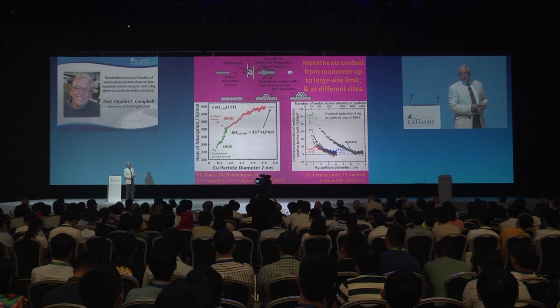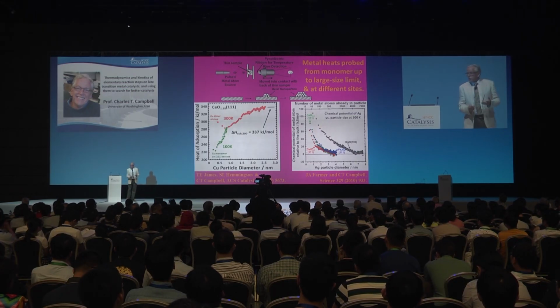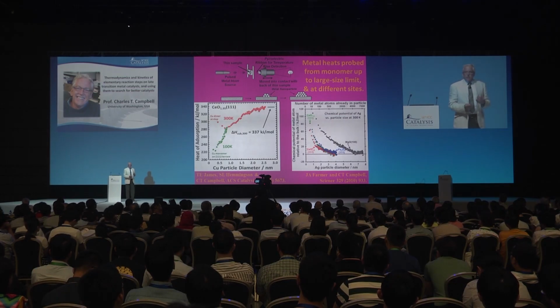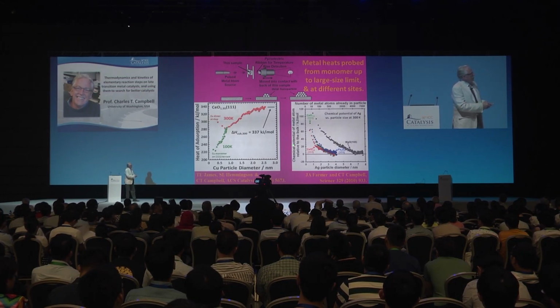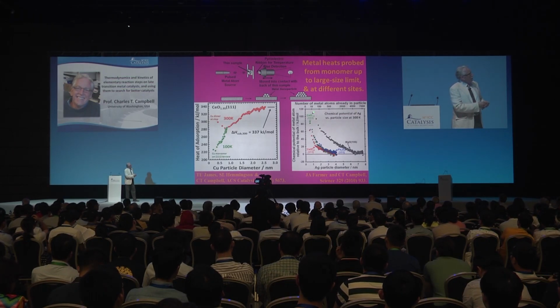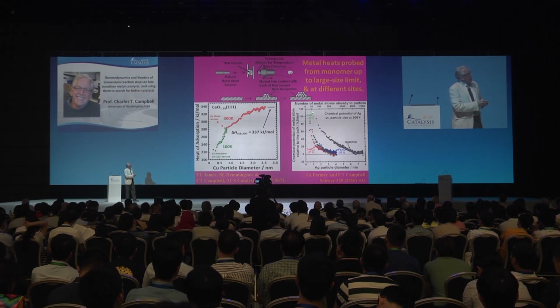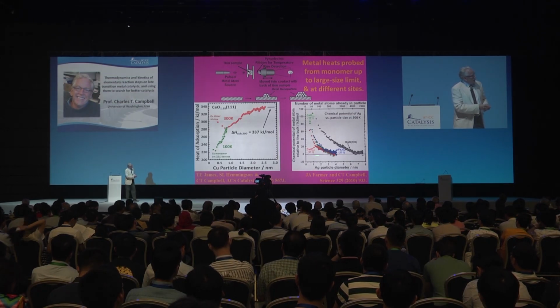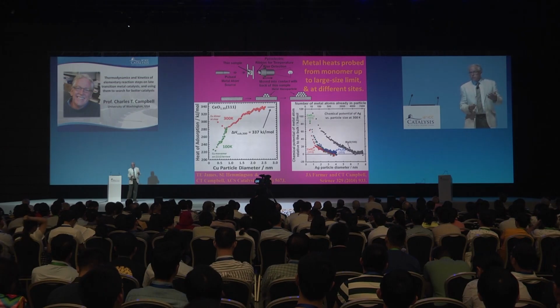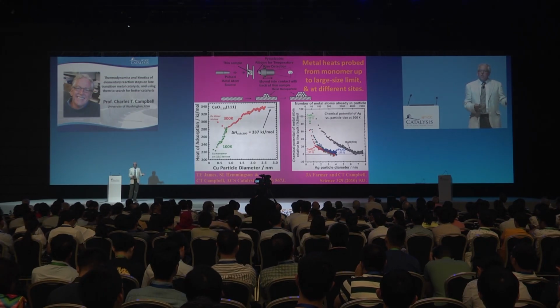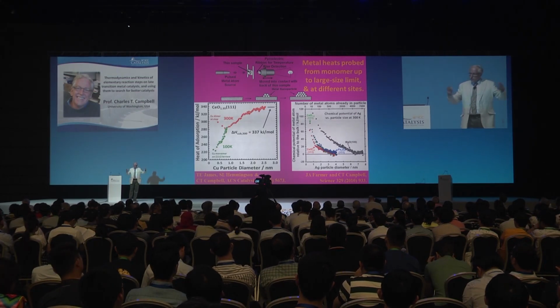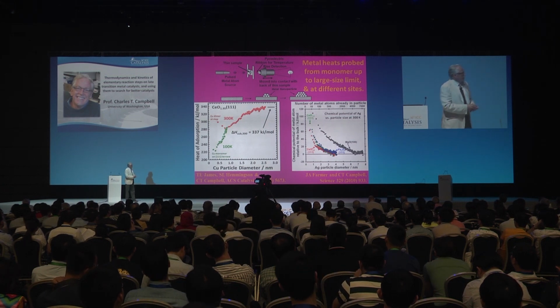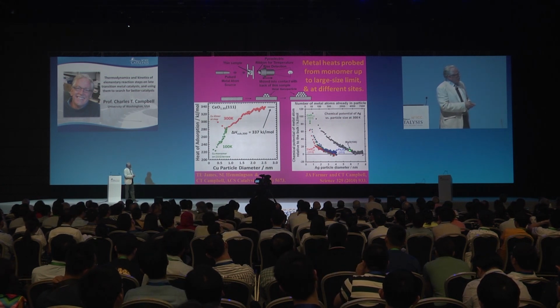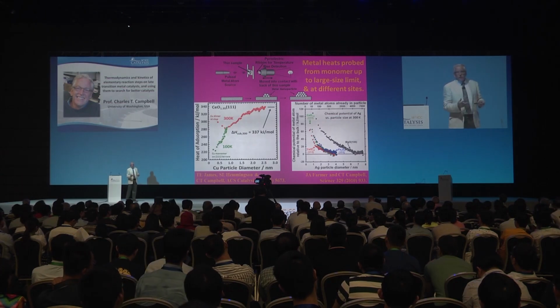We can take these type of data and extract out of that, basically flipping this axis upside down and re-zeroing, the change in the chemical potential of the metal atoms in those particles as a function of the particle size. And the chemical potential starts very high for small particles, and it decreases, eventually leveling off at 0 on this plot, which is the chemical potential of a metal atom in the bulk, infinitely large particle of the metal. And this decrease is the thermodynamic driving force for sintering.